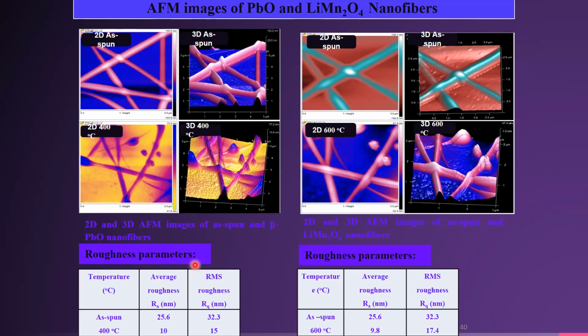Here, the roughness parameters of lead oxide and lithium manganese oxide fiber samples, average roughness and RMS roughness values, are depicted in this table. It is found that with the increase of calcination temperature, the roughness parameters are decreased. Here, the as-spun nanofiber sample shows an average roughness of 25.6, while in the case of 400 degrees centigrade calcinated it is 10 nanometers. RMS roughness of the as-spun nanofiber sample is 32.3 nanometers, while in the case of the calcinated nanofiber sample it is 15 nanometers. So the average roughness and RMS roughness decrease with the increase of temperature. Similarly, the lithium manganese oxide nanofiber sample.